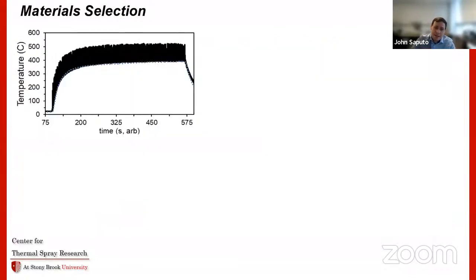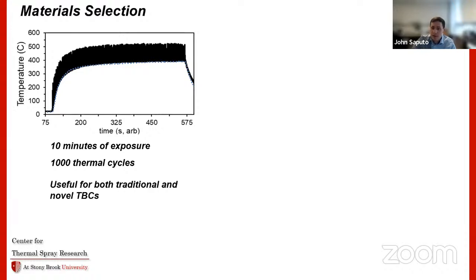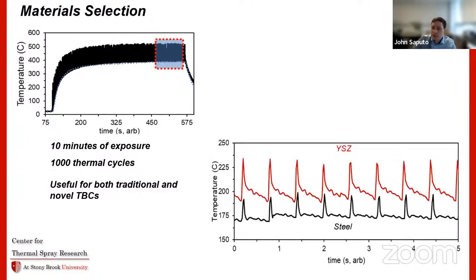So the data that you get out of this looks something like this. Each one of these cycles sort of rapidly swings back and forth. This is 10 minutes of continuous exposure, about 1,000 cycles, and it's useful for both traditional TBCs and these novel materials that I was talking about. You can zoom in on one of these little sections and see what happens during this cycle. So the steel is the black line, zirconia, traditional TBC, is the red line, and there's two interesting things that you get out of it.